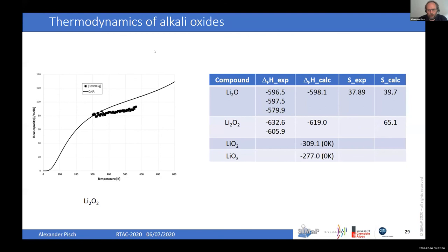I think using ab initio molecular dynamics, you can calculate pressure dependence. But again, it will take a lot of computer power to do so. There's no way of doing it experimentally. Experimentally, there are experiments, but they are limited to a certain amount of pressure. And they are also very tricky to measure because very often you have diamond anvils, and at moderate pressures you can do DC measurements in pressure cells, but if it comes to very high pressure, it's tricky.